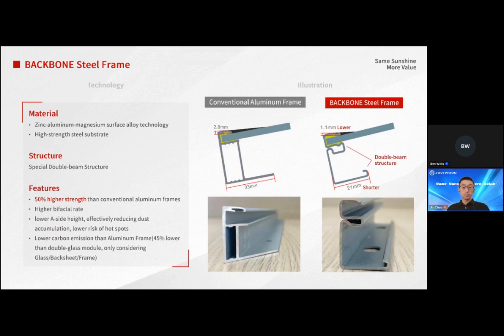Now let's move on to the backbone steel frame, which is another critical component of the windproof module, designed to improve durability and efficiency. On the material, the backbone steel frame uses a zinc, aluminum, magnesium surface alloy and a high-strength steel substrate, which provide durability compared to traditional materials. And on the structure, the frame is built with a special double beam structure. This design enhances its strength while also optimizing the module's overall performance. The frame strength is 50% higher compared to conventional aluminum frames, ensuring better mechanical protection.